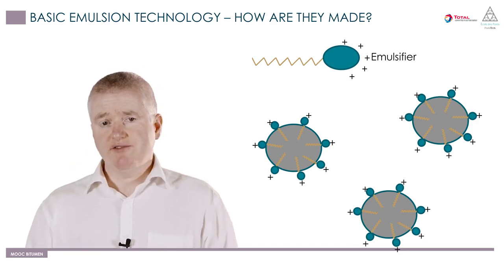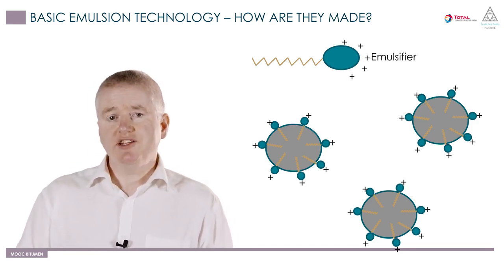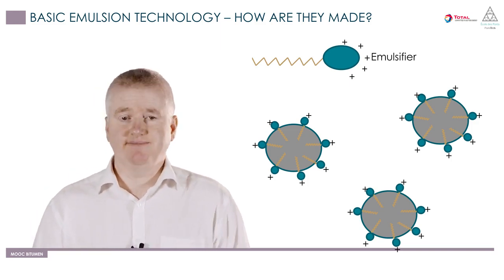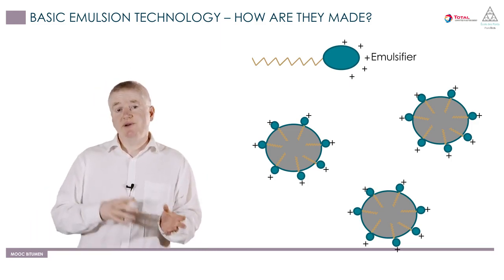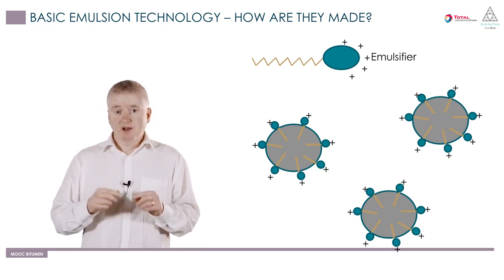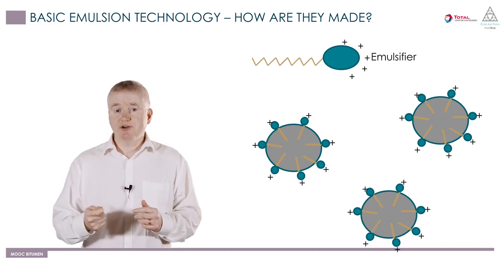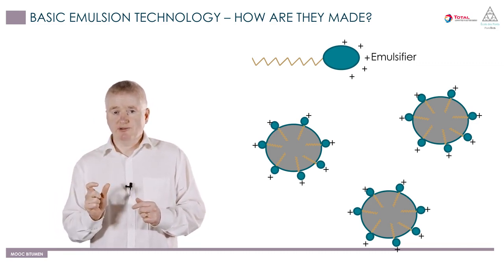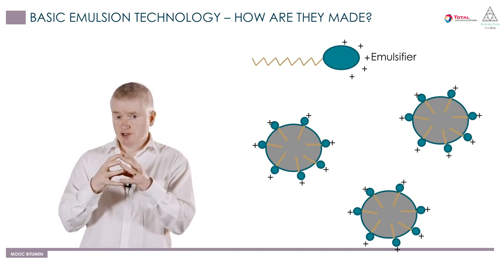This emulsifier is dispersed in water, and then to activate the part of the molecule that is like water, we add acid. In simple terms, the bitumen is milled with the water phase containing the emulsifier, with the result that the bitumen is dispersed in very small globules surrounded by these emulsifier molecules in discrete micelles or structures.